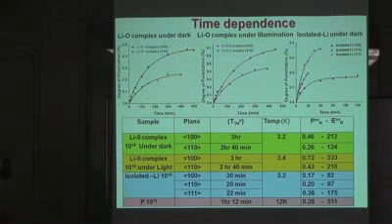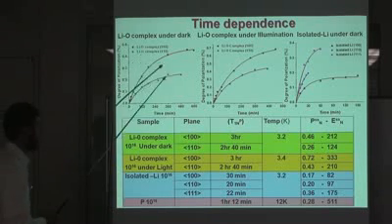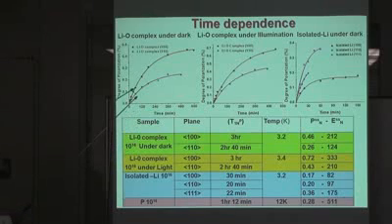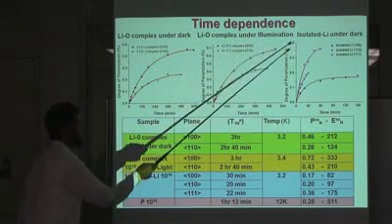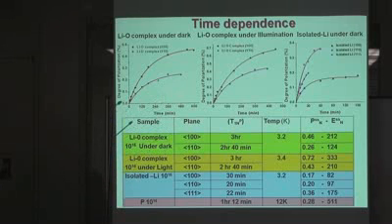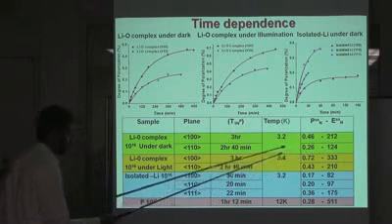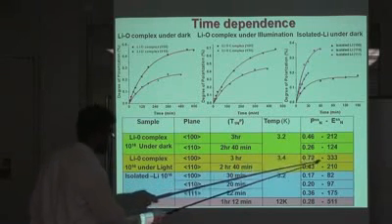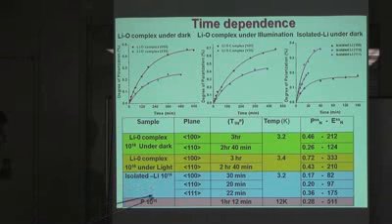Now I want to show you the time dependence. I measured the time dependence of the lithium oxygen complex in the dark and under illumination, and isolated lithium in dark condition. The maximum polarization, not enhancement, that we measured in the lithium oxygen complex is 0.72%, and